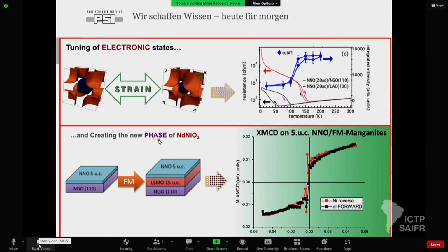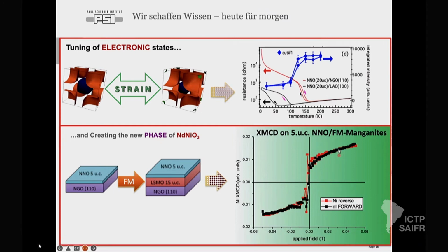And for the last slide, I would just like to summarize. With strain, we are able to alter the electronic states and the Fermi surfaces, and with the buffer layer, we are showing that it is possible to create a new phase, because neodymium nickelate is not ferromagnetic, but we are able to show that ferromagnetism is induced via the buffer layer.